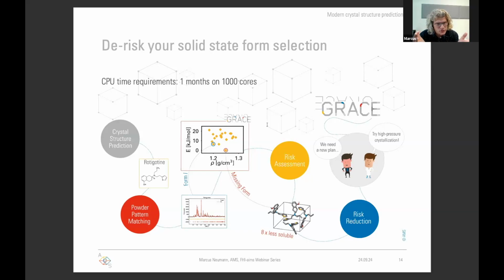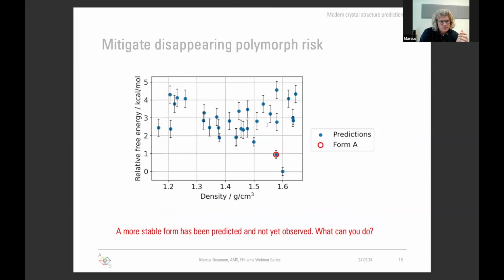We would be able to put a solubility difference on the difference between the two polymorphs, and we would say, okay, the missing form is 8 times less soluble. The customer would then say, oh, this is very, very dangerous. And then together with the customer, we would enter into a risk reduction strategy, either to make or to avoid that form. And in pharmaceutical companies, that triggers real decisions. So, for instance, if they have a case like this one, where a landscape has been built and an experimental form has been placed on the landscape, and according to the error bar, the most stable predicted structure is truly still missing and is truly more stable.